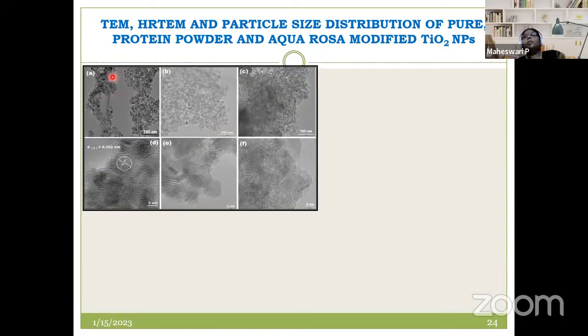Now, from the TEM and HR-TEM analysis, we can see this particular part. This is the normal TEM analysis, and this is a high resolution TEM analysis for the synthesized TiO2. And this one, the Aquarosa modified TiO2 for TEM, and this is for the HR-TEM. Similarly, this is for the protein powder modified one, and this will be the HR. When you want to go very close, at very high resolution, you go to HR-TEM analysis, where you read around the 5 nanometer scale.